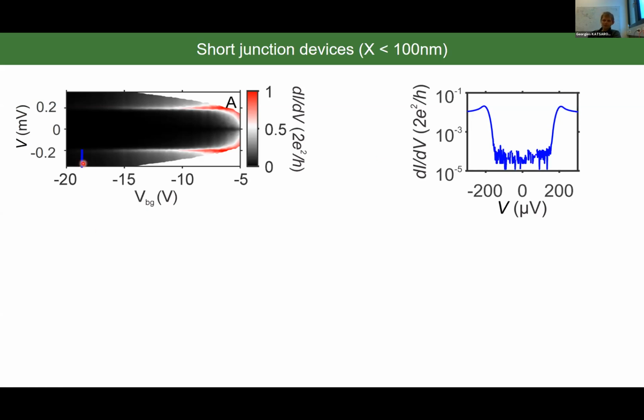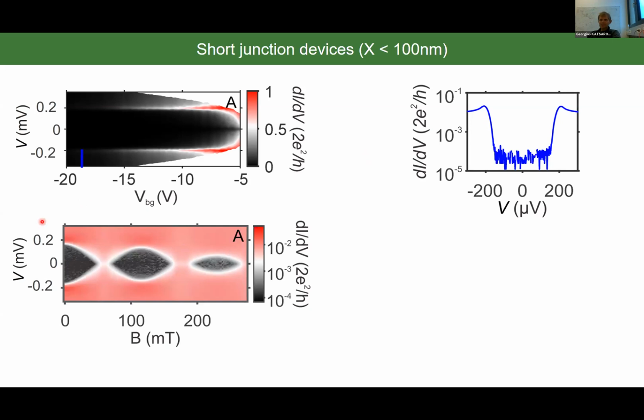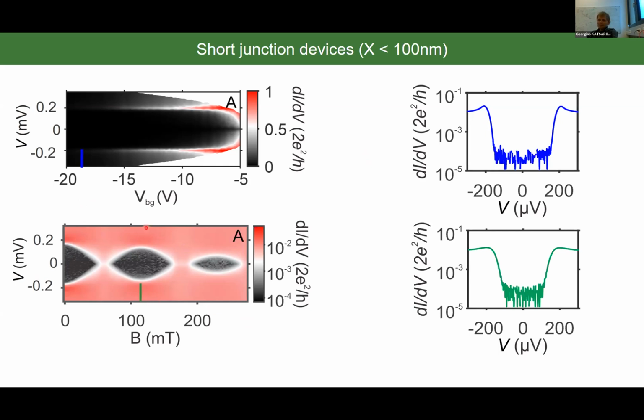And now we fix our gate voltage and we start sweeping the magnetic field. So again, differential conductance versus bias, but now sweeping the magnetic field. And as I told you, if you now sit in the middle of the first lobe and you take a line scan, you can see that the gap is still hard. The only thing which has changed is that the gap has become slightly smaller. If now you check this measurement, obviously you observe that there is no zero bias peak. Please remember that according to theory, if we would have Majorana zero modes in this system, we should see a zero bias peak in the first lobe.